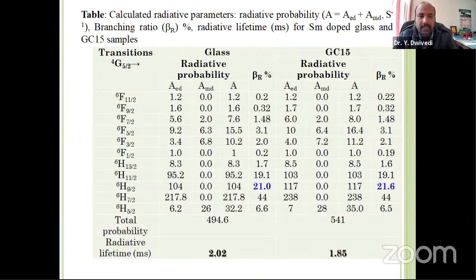We have also estimated some radiative parameters, and particularly in the case of glass and glass ceramics, one transition, 6H9/2, which is a very hypersensitive transition, that value actually increased from 21.0 to 21.6. So this slight increment, even so, is very important.